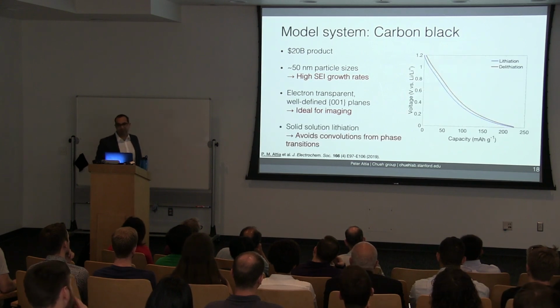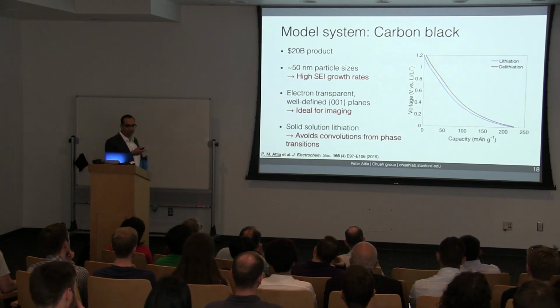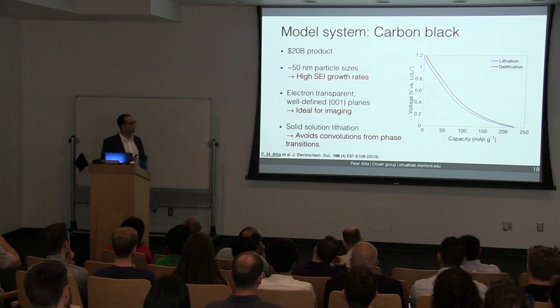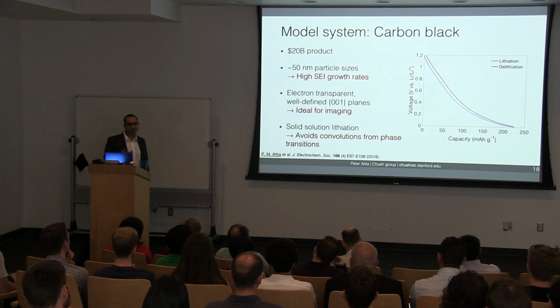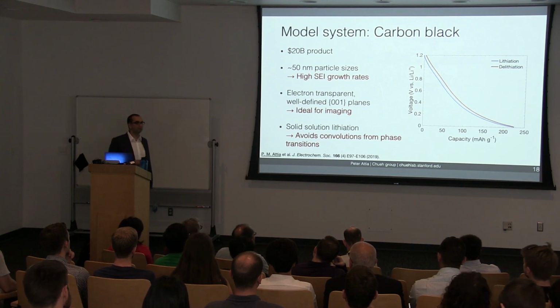And this last major advantage is solid solution lithiation. We saw a few slides ago that graphite has these phase transitions. Carbon black doesn't have these phase transitions in solid solution, and because its voltage curves are smooth, it makes it easier to analyze data. So in a lot of ways, carbon black is really an ideal carbon system for SEI studies.